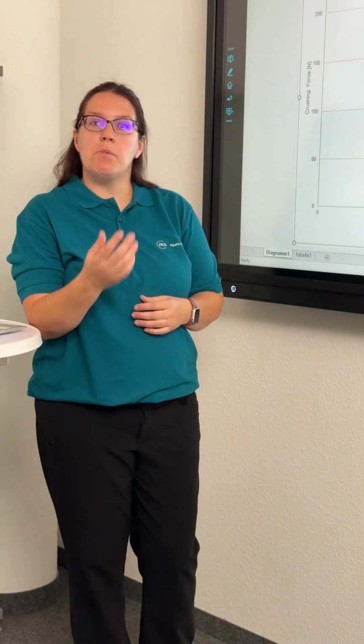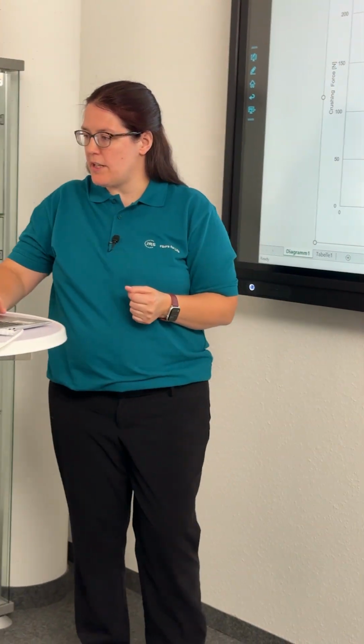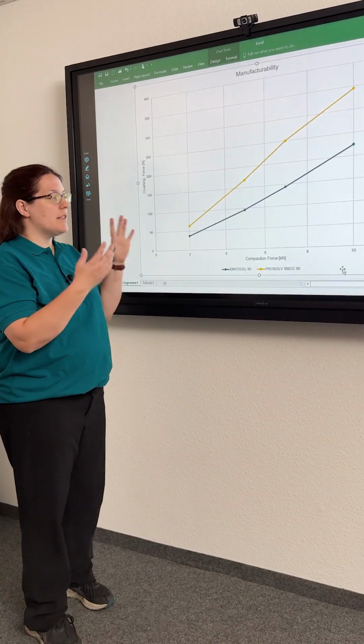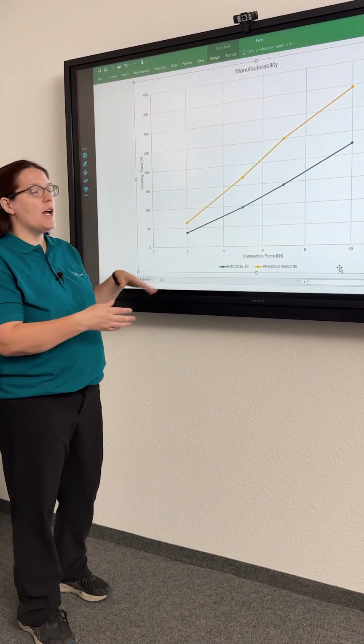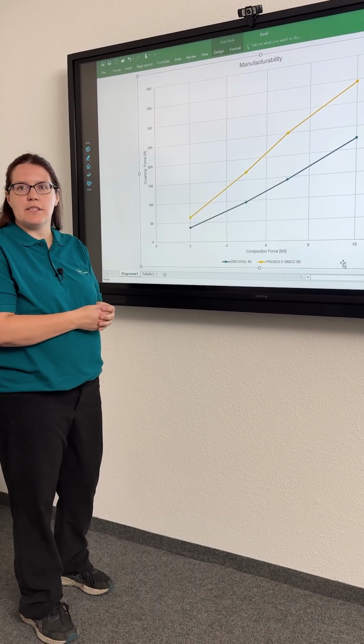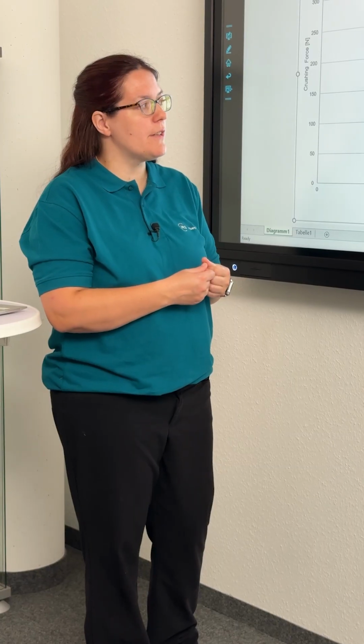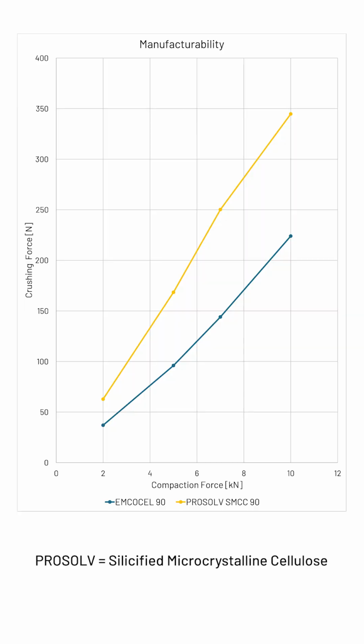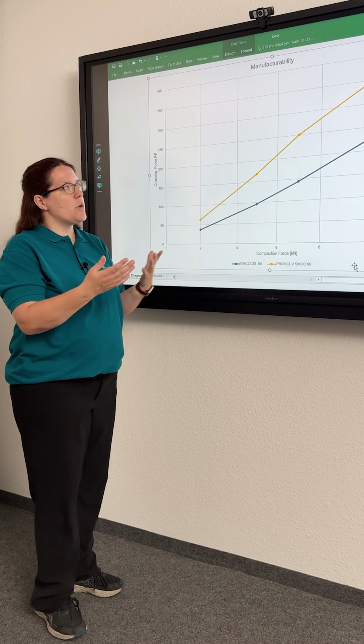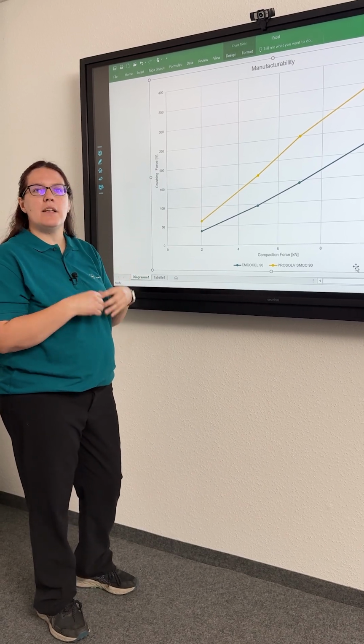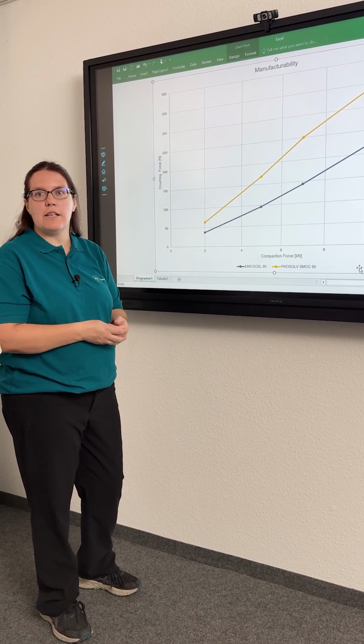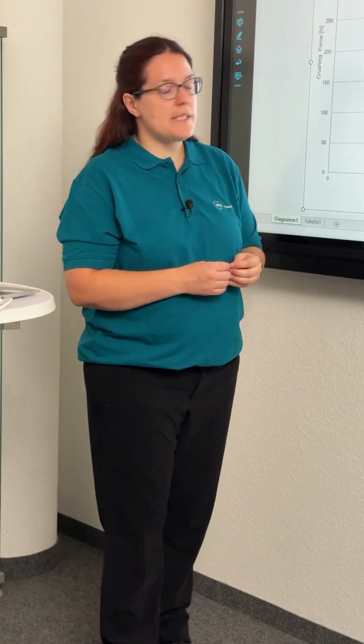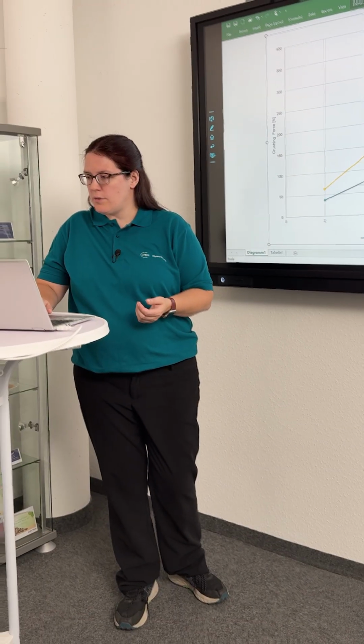Now let's take a look at how some other materials respond in manufacturability. First, let's take a look at the same size of material, but actually silicified microcrystalline cellulose rather than the non-silicified version. And here you can see that you also have a fairly linear response of hardness to compaction force, but actually your tablets at any single compaction force are a lot harder. So this shows that there's even a little more compactability in the silicified version of microcrystalline cellulose than in the standard. Now let's take a look at a filler that is often used to improve flowability.